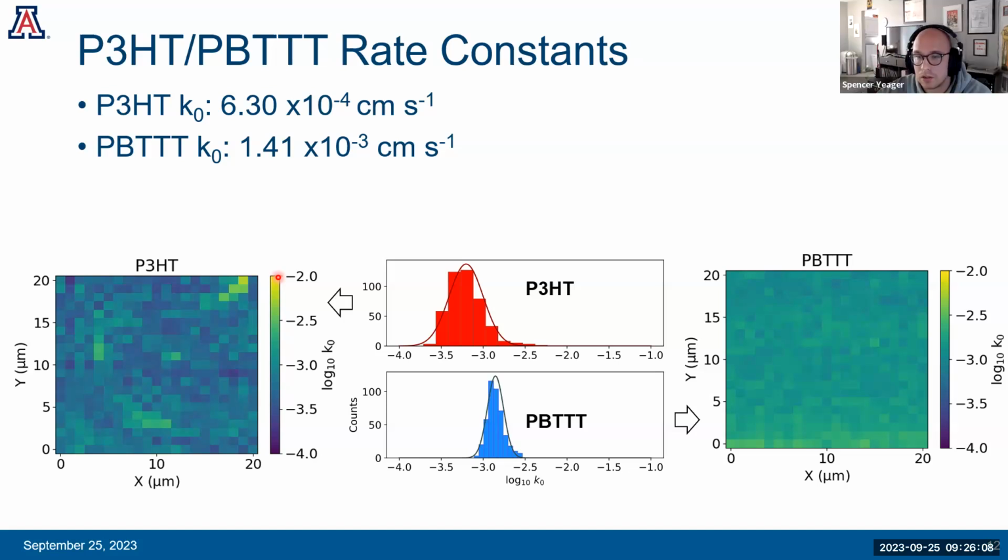Yeah. The domains, right? The crystallite size in P3HT. The size that's associated with either the amorphous or the crystalline regions tends to be a lot smaller than that, at least in order of magnitude. But as I understand it, you're interpreting the maps as being from amorphous domains and crystalline domains. Aren't you averaging over like 100 domains?